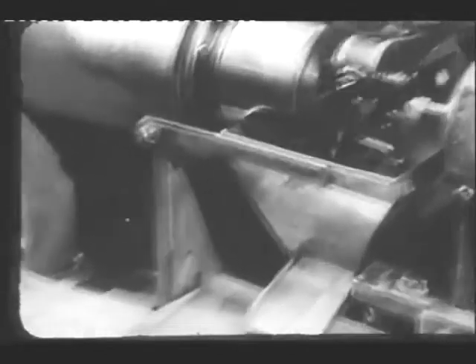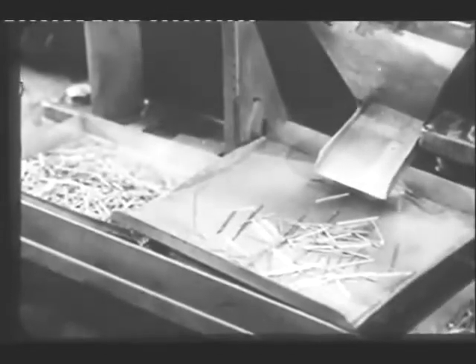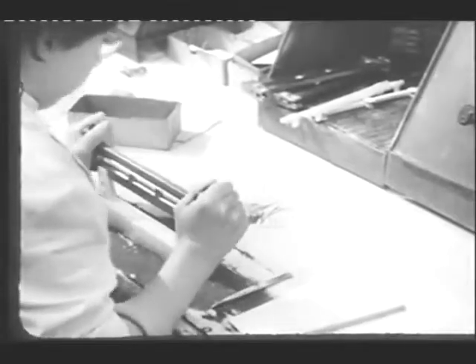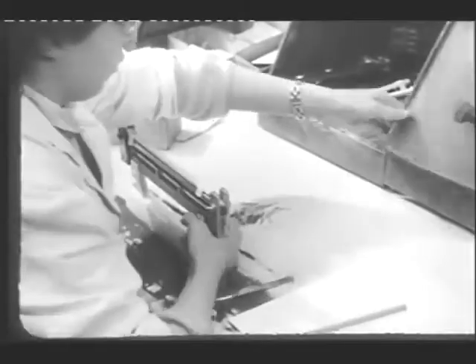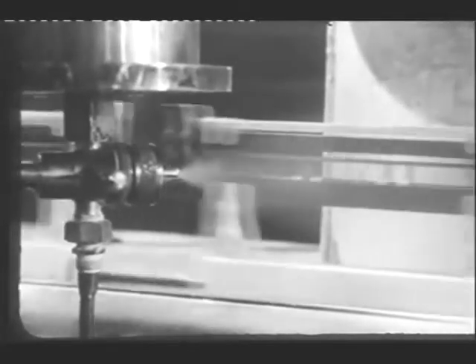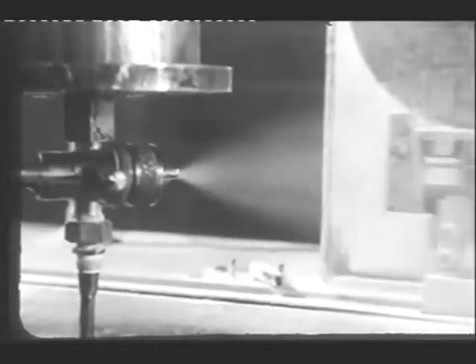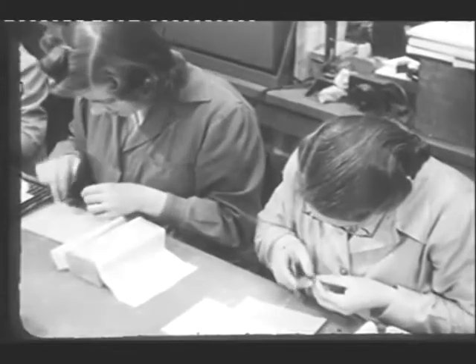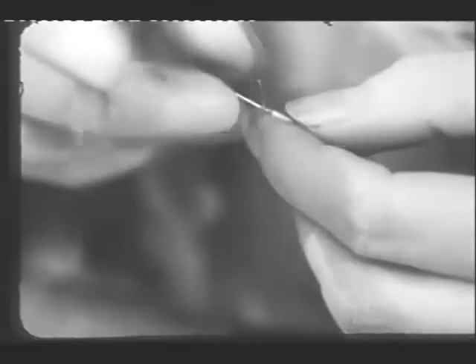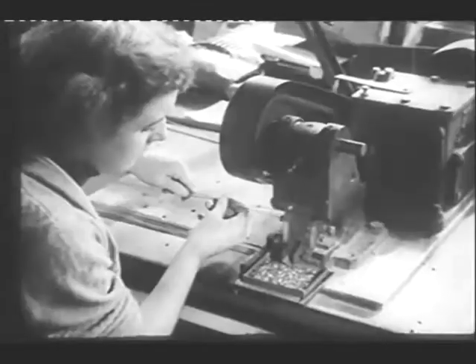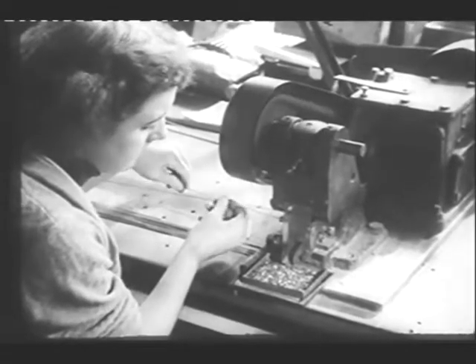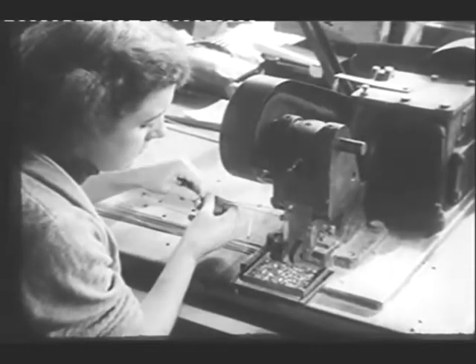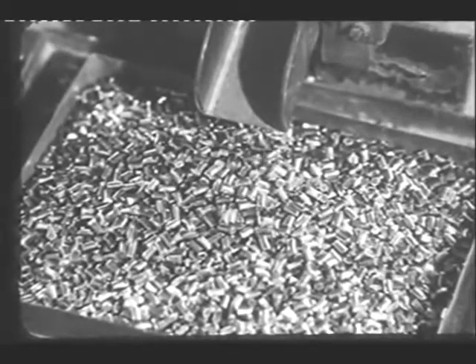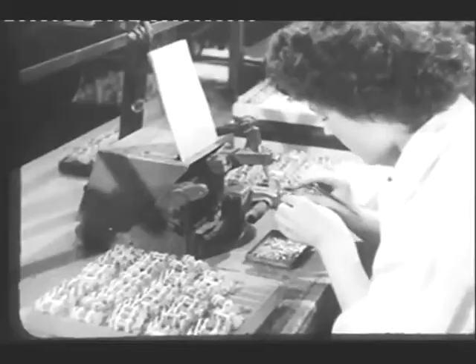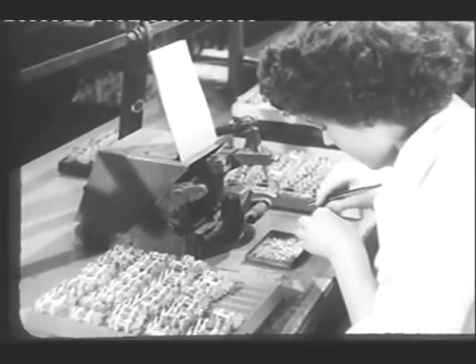Nickel cathode tubes are cut to length, mounted in frames, and sprayed with barium and strontium carbonates, from which the emissive surface is produced later on. In this case, the heaters are inserted into the coated tube at an early stage. Now you can see that most important component, the getter, being made. It is being electrically welded onto a finished assembly.